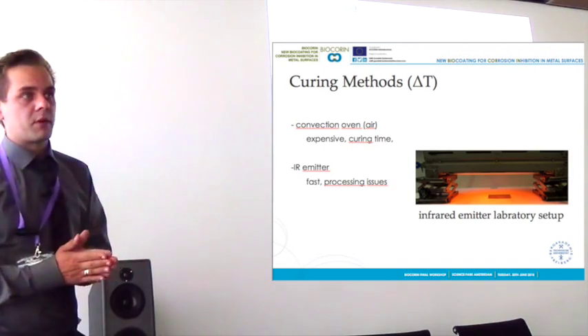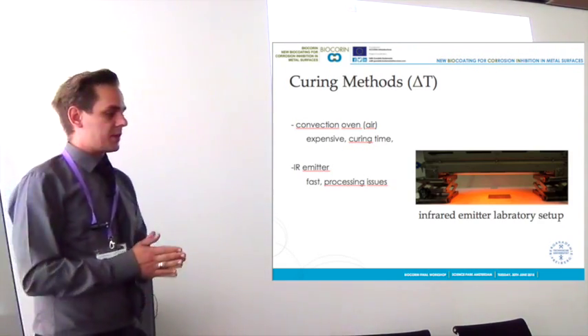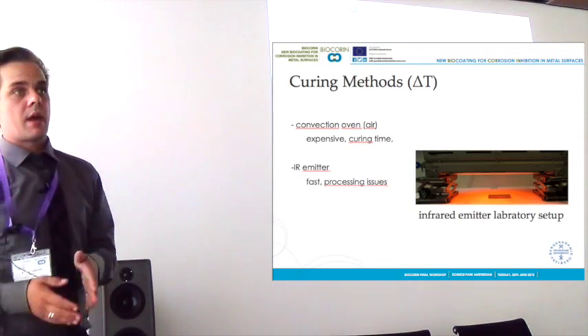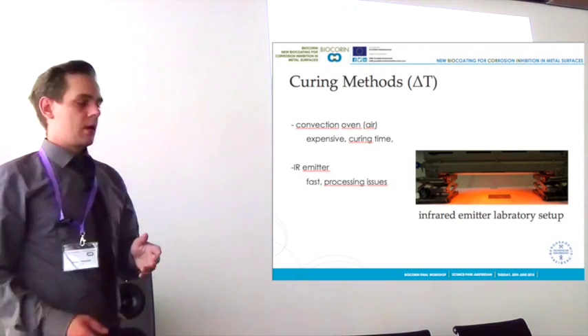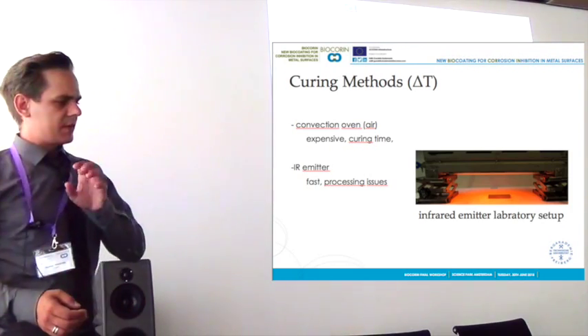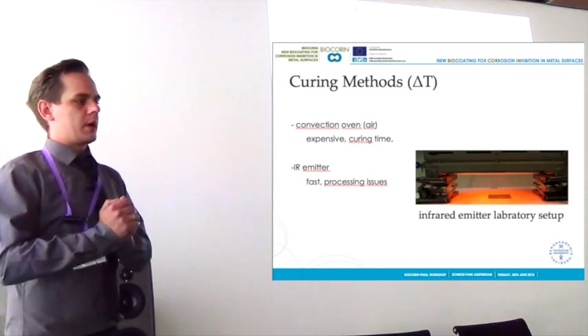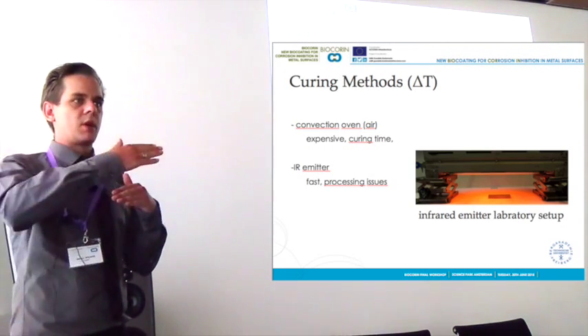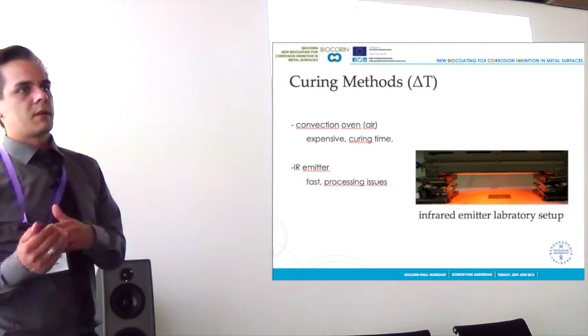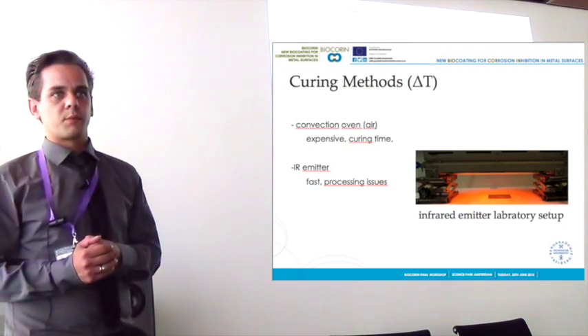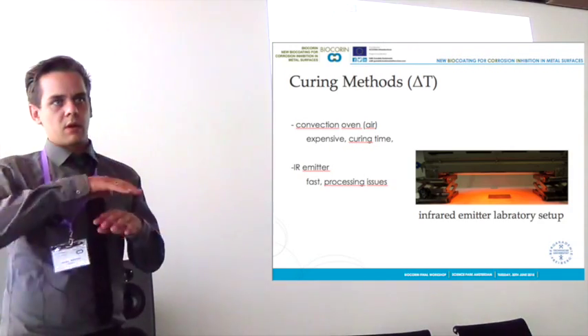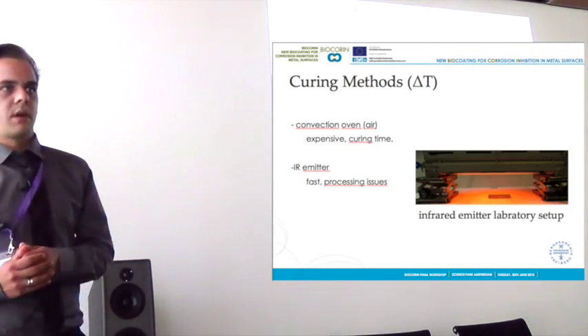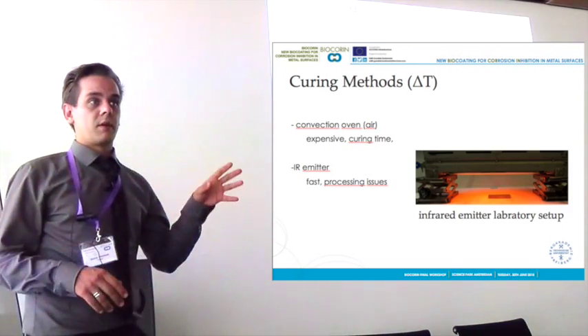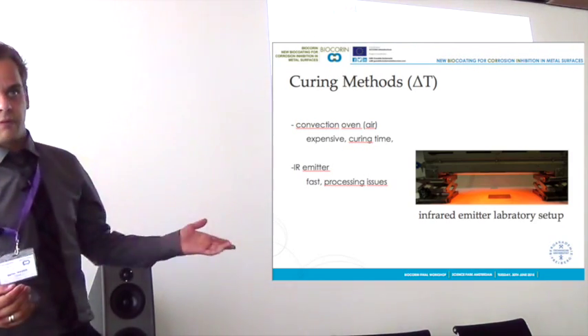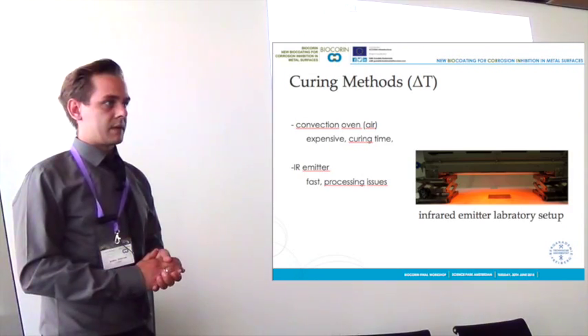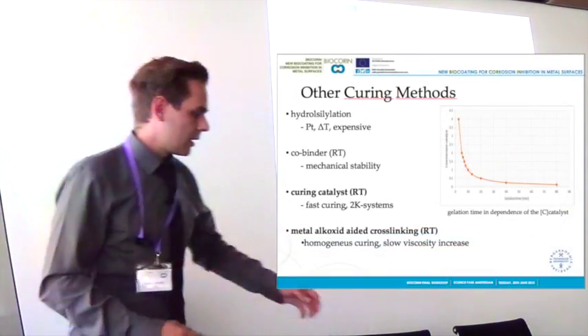Another method that we introduced, which is not very often used for sol gel chemistry, are IR emitters, infrared emitters. It's a very fast process. You can accelerate the curing process 10 times. But you still have a few processing issues, like you have to have quite a constant distance between the plate that you want to cure and the IR emitters. That means if you have something very flat like we used in the project, it's quite easy. But if you have something round shaped, you have to move the IR emitter around, and that makes the process difficult, because if you have a change in the distance, you will have a change in the protective behavior of the coating, and that makes difficult shapes not easy to cure.